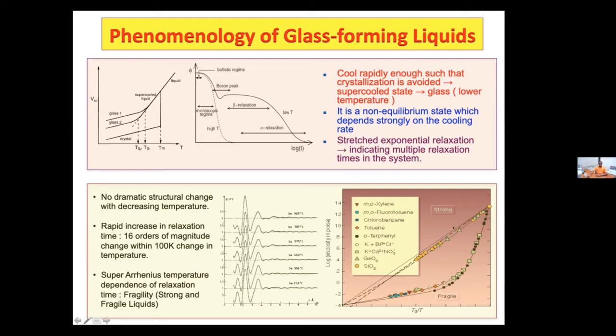This enormous change is a puzzle to many, because if you look at the corresponding structures, for example the typical pair correlation function that you can obtain via various scattering experiments, it doesn't change. For example, in this one, where selenium is cooled to low temperature, viscosity rises by a factor of 10 to the 13, but then you see the g(r) looks more or less very similar. This is one of the puzzles that the glass community has been facing for maybe the last 50, 60 years, and this is the reason why it's one of the unsolved problems.